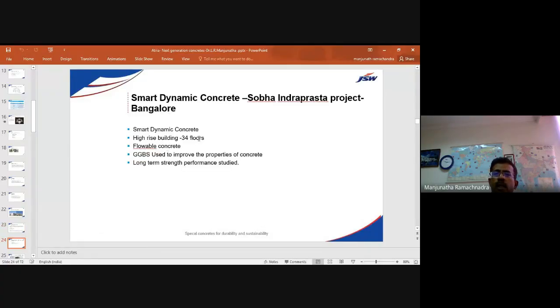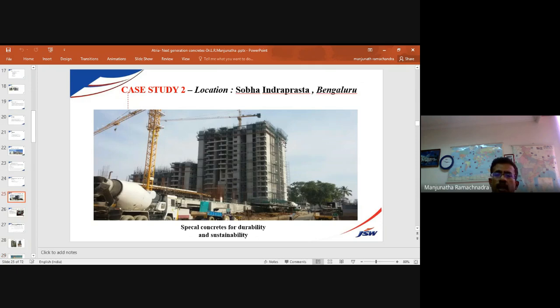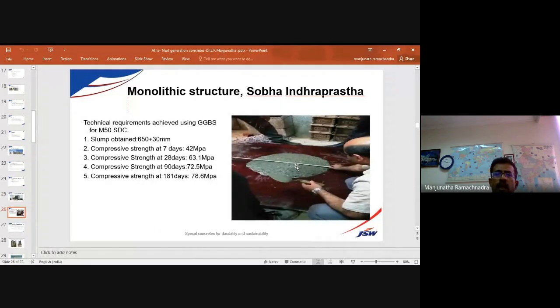So many projects are using it. Where they use smart dynamic concrete, 34 floors, flowable concrete. This is the construction they have done using smart dynamic concrete. We supplied GGBS there, and we have done a lot of study. You can see the flow of the concrete. And also, we have studied compressive strength from 7 days to 181 days. The M50 grade concrete has developed 78 MPa, almost 30 MPa more than the required strength.